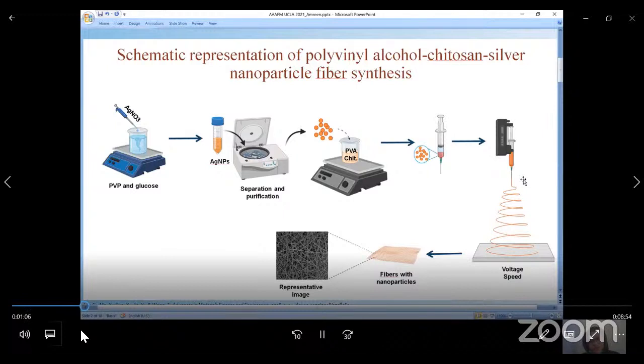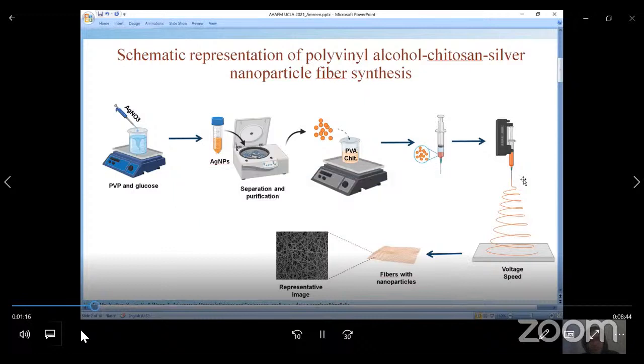Later, in the second part, polyvinyl alcohol and chitosan were used as a fiber solution in which the silver nanoparticles formed in part 1 were incorporated, and then electrospun with optimization of voltage and speed. The fibers obtained have particles in them, and this is the representative image. This is the scanning electron microscopic image of the fibers, confirming the morphology and formation of the fiber.